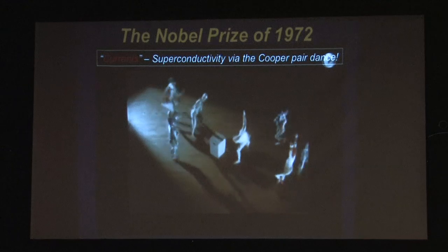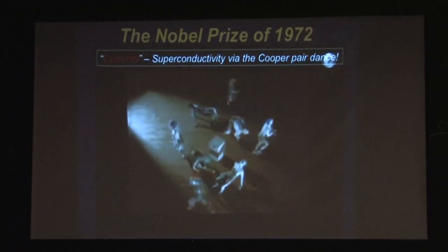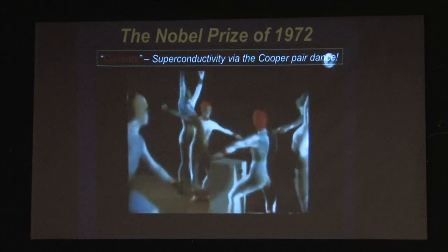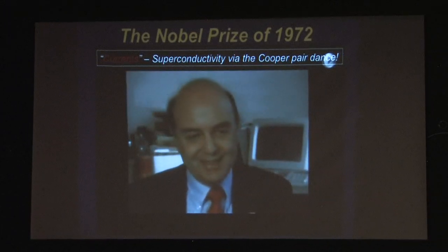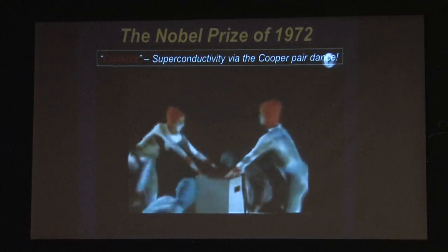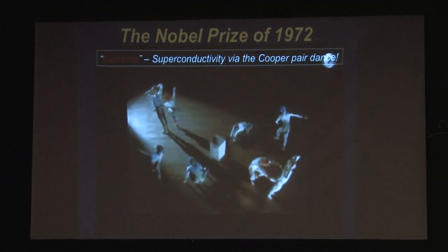So here's the thing. You're looking at an explanation for old superconductors, which were superconducting at lower temperatures. The problem with this theory for the new superconductors, which operate at 77 Kelvin or higher, is that at these high temperatures, atoms move. Because the temperature is high, they move around everywhere. Because the atoms move, it's very difficult for this lattice, connected through the matrix analogy, through these positive ions that I told you. There's an electron-phonon coupling; these lattice vibrations are called phonons, and they were coupling the two electrons together. With these high temperature superconductors, these vibrations are too rapid to allow that pairing to occur. So some other mechanism occurs, and you're going to hear more about that from Thomas later on.